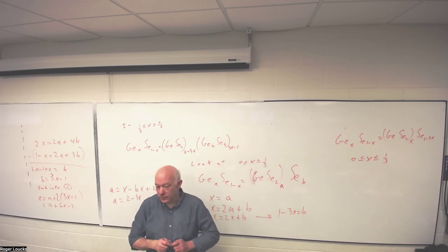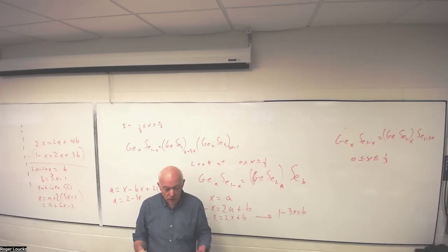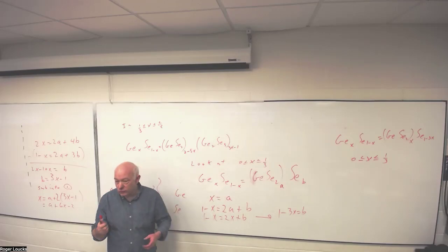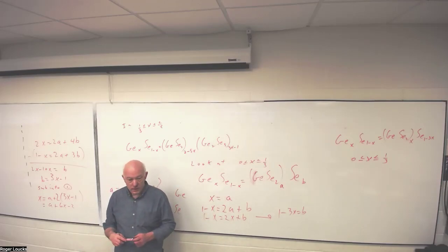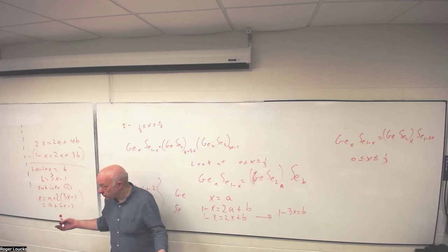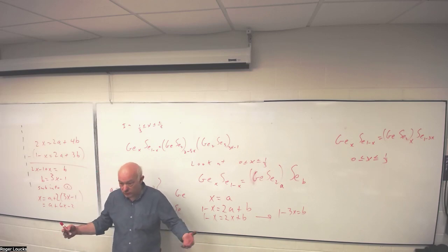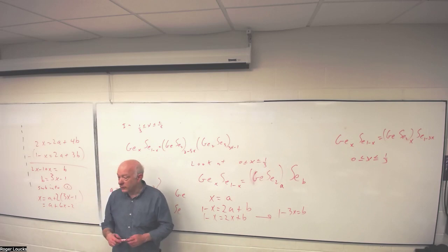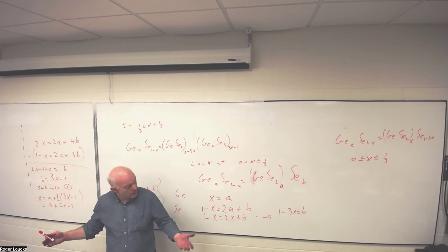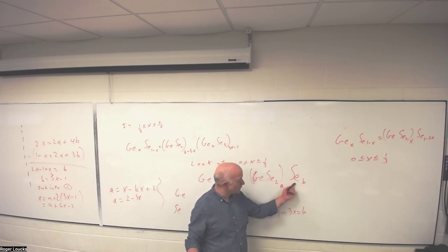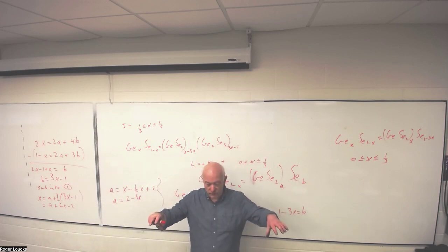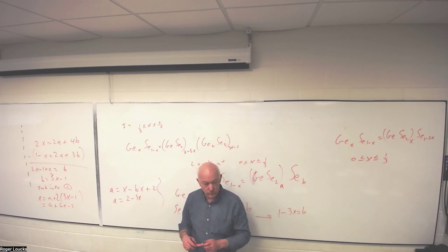So now we have to start counting bonds, and we'll start that on Monday, but let's just go, counting constraints. So what are we going to have here? What kind of constraints could we have? Angular constraints, and we're going to have to figure out how many angular constraints we have. What else can we have? Linear bond constraints. And if we have these long tails of selenium, what else can we have? Maybe some sort of van der Waals constraint.